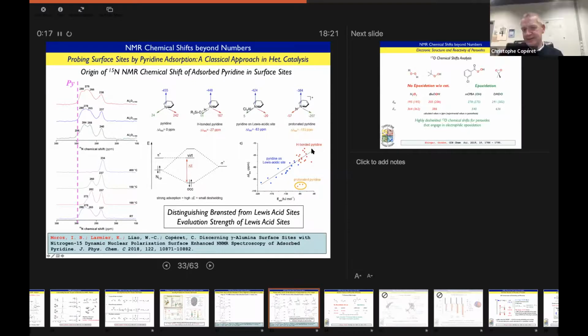So any Lewis acid, Lewis base interaction is actually linear as a function of delta H of adsorption with chemical shift. Well, when you protonate, because now you make a conjugated base, the energy of adsorption is unrelated to the interaction of this newly formed sigma bond, then you're actually off the scale and you have a very shielded chemical shift. And the reason for that is that in contrast to the metal, where you combine a sigma with a low-lying pi star, here you actually quench the lone pair, which is important for the coupling with a pi star. So the origin is just different, basically.